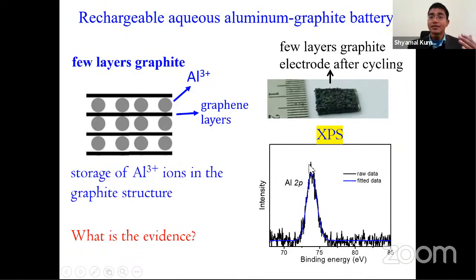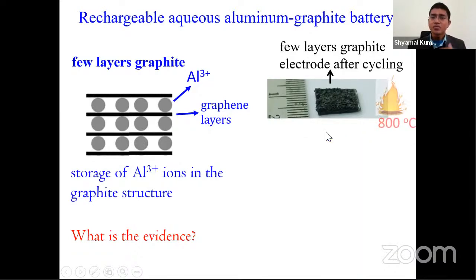It means that aluminum is there, but whether this aluminum is inside this structure or just on the surface, we do not know. To verify that, we use a simple technique. We burned this electrode at 800 degrees Celsius under air atmosphere.